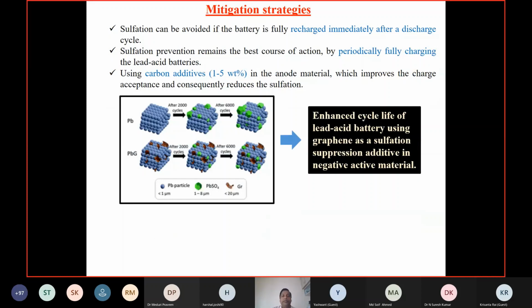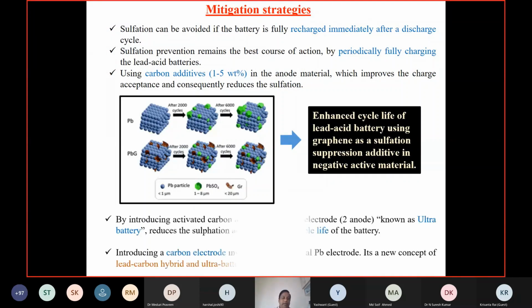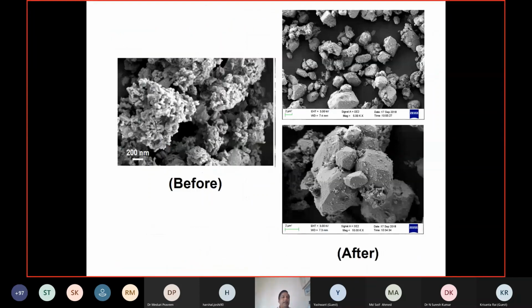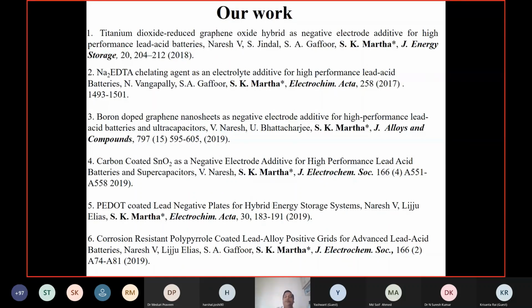So how to reduce the sulfation? It has been seen that carbon additives reduce the sulfation. You can use carbon nanofiber, graphene, graphite, a few percent. We have added these. Let me show you. We have done a lot of work on how to improve the active material utilization. We have done in situ work on how to improve the formation efficiency from 3 cycles to 1 cycle, and how to reduce sulfation. If sulfation is reduced, it improves the HRPSoC application. Our goal is to reduce sulfation, improve the formation efficiency and improve the active material utilization.